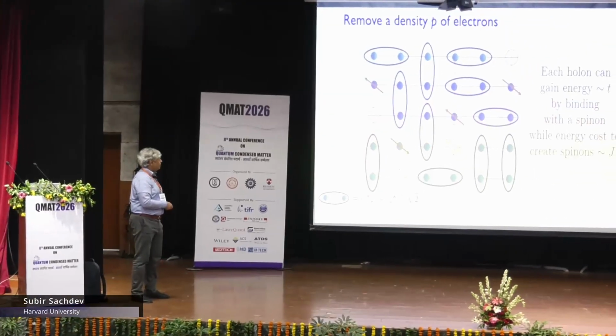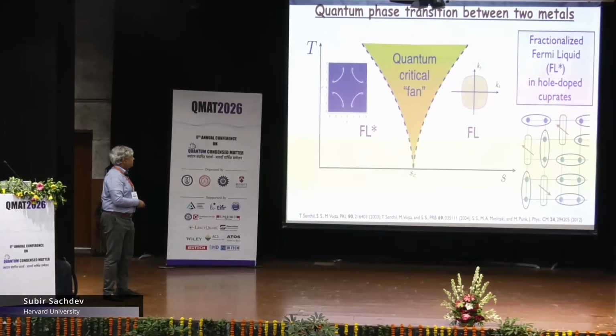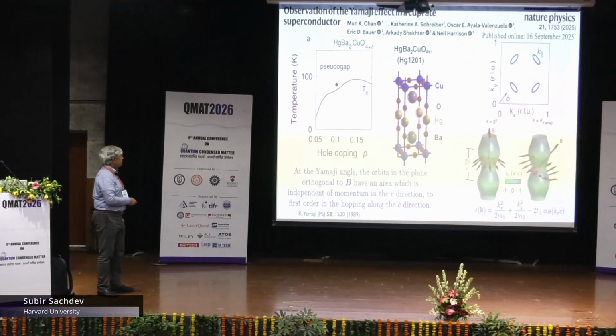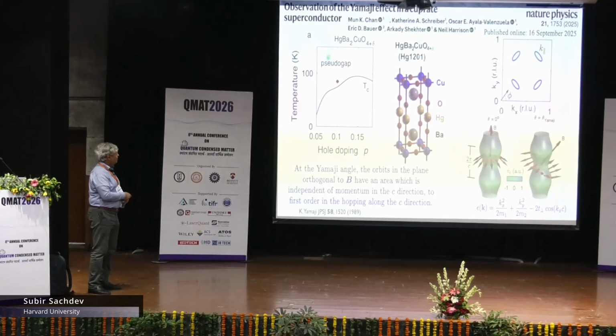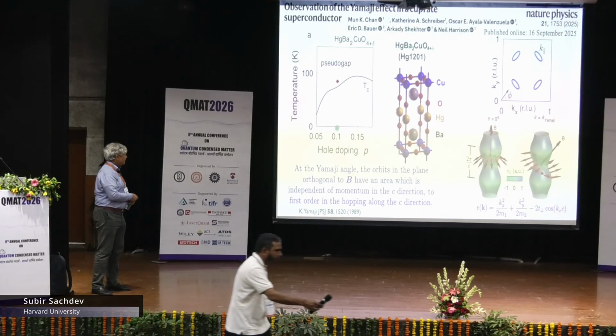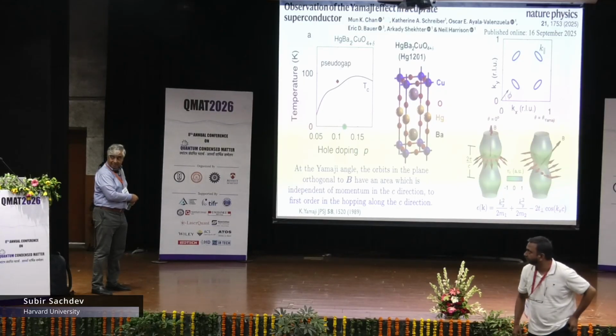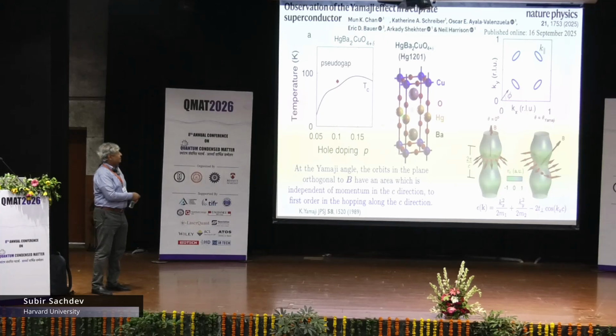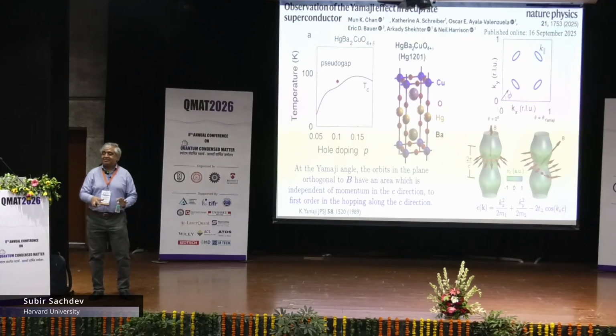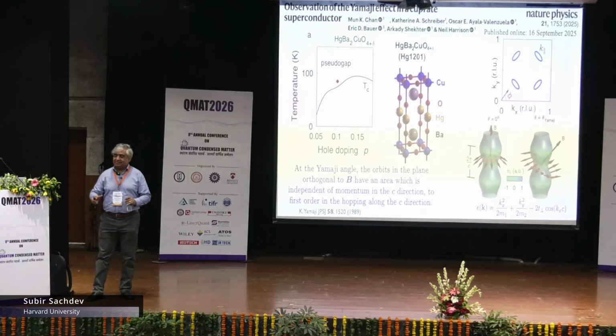So this experiment I went through very quickly. This Yamaji effect experiment is also done above Tc. It's done at these higher temperatures. So at this temperature, there is no sign of charge density wave order or anything like that. What you were referring to was experiments done down here at low temperatures. And there you do see the charge density wave order at very low temperatures, even in the same material. So there are some low temperature states which are, in the end, conventional, in the sense that they can be understood by some Hartree-Fock theory, the superconductor or the charge density wave.